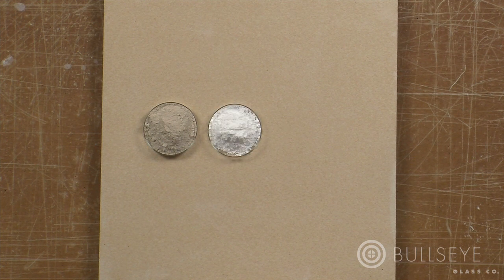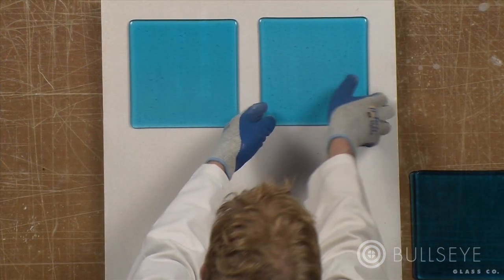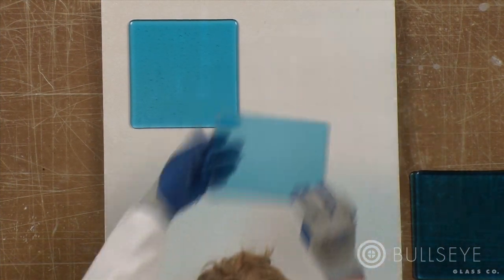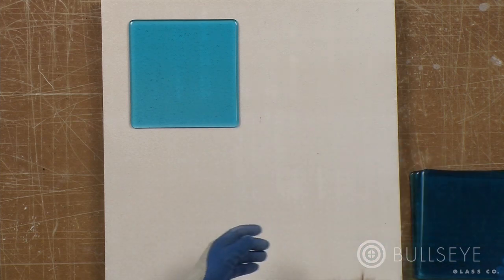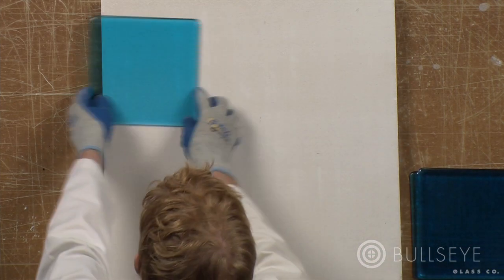Bullseye Shelf Primer is a simple mixture of 3 dry ingredients: kaolin, alumina hydrate, and a pink colorant which is composed of organic material. The slow dehydration of the kaolin and alumina hydrate throughout the upper temperature range of the fusing process prevents the glass from forming a bond with the ceramic shelf.